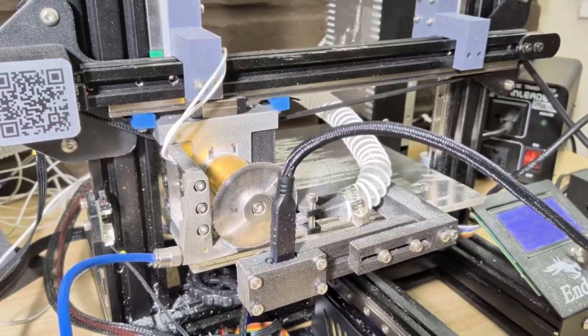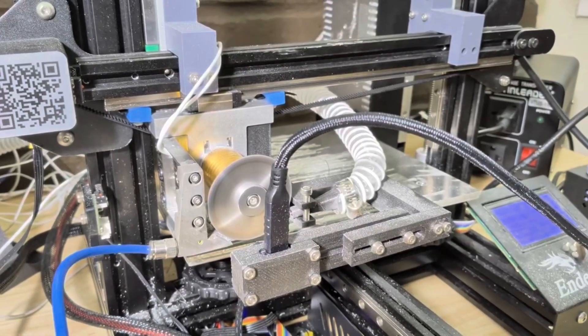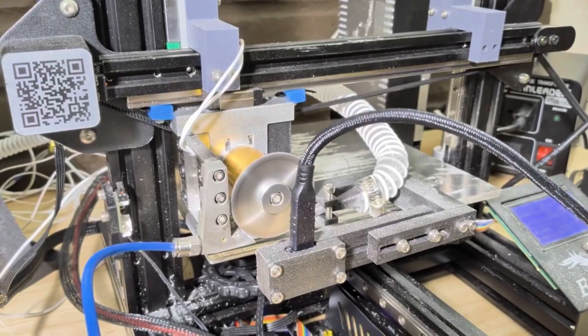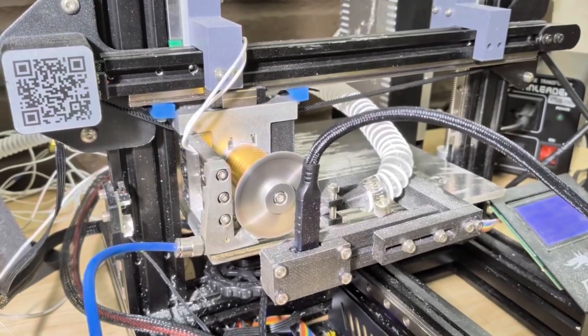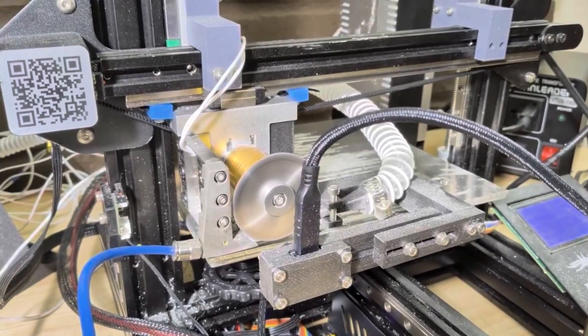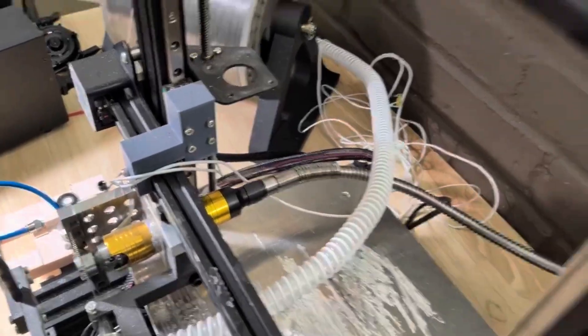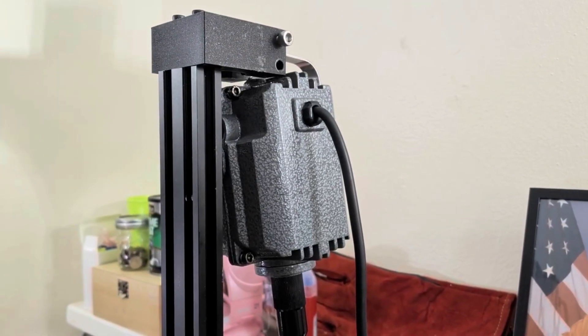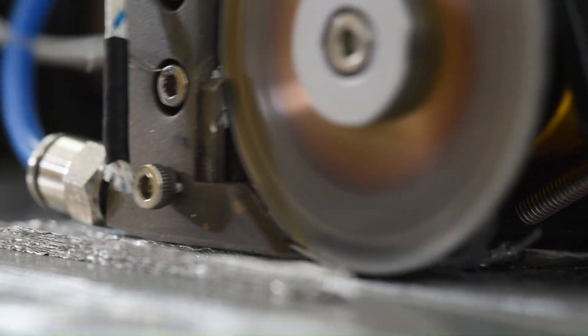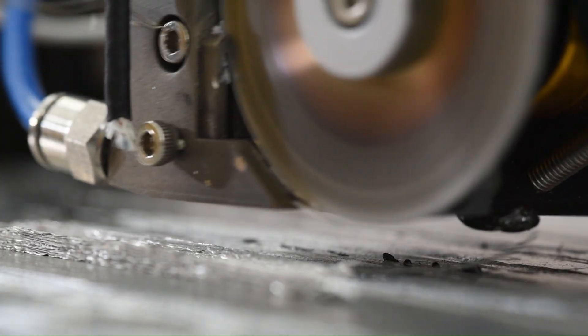The print head consists of a heated wire guide that feeds the aluminum wire into the contact patch underneath a turndown high-speed steel saw blade. Using a flex shaft handpiece, which is connected to a die grinder motor, we can spin the saw blade at about 30,000 RPM. This is enough to plasticize aluminum and to stir it into the underlying aluminum substrate, allowing us to build up parts.